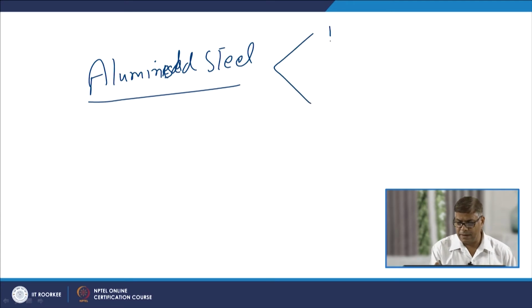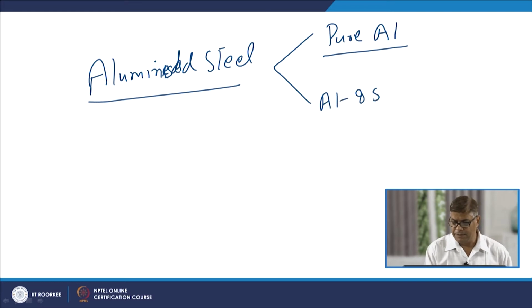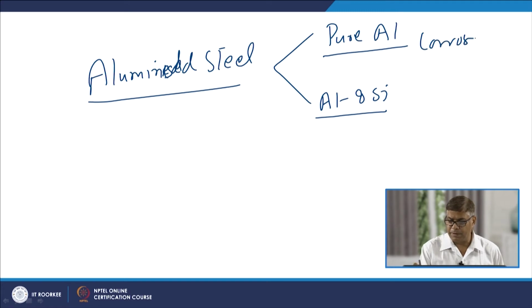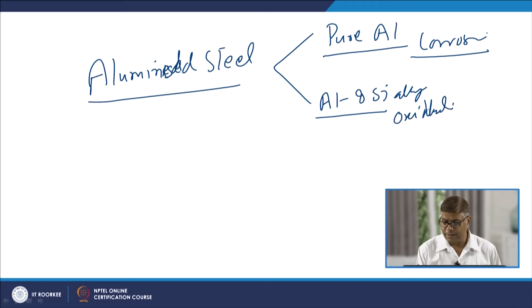So, we will be talking about first the aluminized steels. As I have said, these can be coated using pure aluminum or aluminum with 8% silicon using the hot dipping method. When pure aluminum is used, it primarily helps in improving the corrosion resistance, and when the aluminum 8% silicon alloy is coated, it helps to increase the oxidation resistance at a high temperature, around 1200 degrees Fahrenheit.